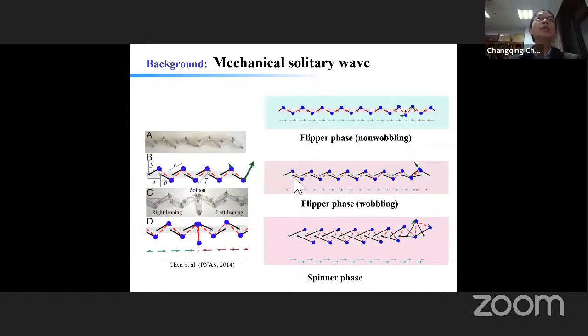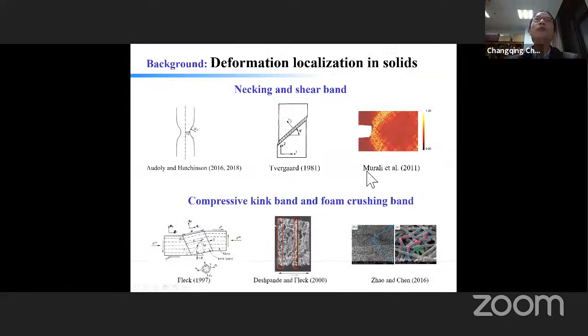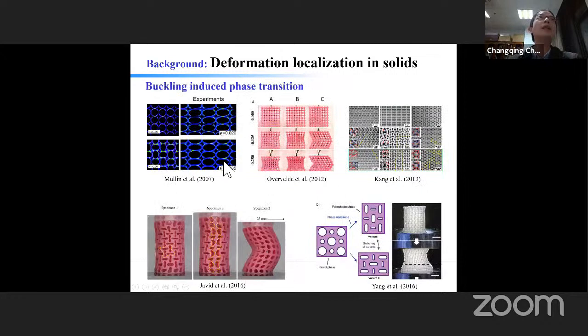So we talked about localized deformation in tension, for the crack, for the necking, and in compression, say for a composite, you load it in this way and shear it this way, you always observe kink bands, and also in foams, and in fiber network materials, we also observe highly localized deformation. In addition to conventional materials, in mechanical metamaterials we also observe buckling-induced phase transitions shown in this slide, as published by many high-profile groups around the world, and it also shows highly localized deformation.